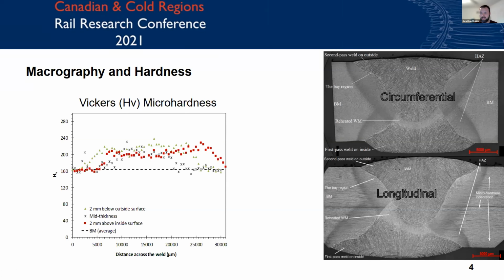Micro-hardness is an excellent method for testing welds because there's always the potential for quite a bit of variability across a weld, given all of the complex microstructural things that are happening. And what this testing shows is that in all cases, the hardness through the weld was higher than that of the base metal, which was about 160 HV, and we did not see any significant numbers below that standard, which is exactly what we would like to see across a weld.